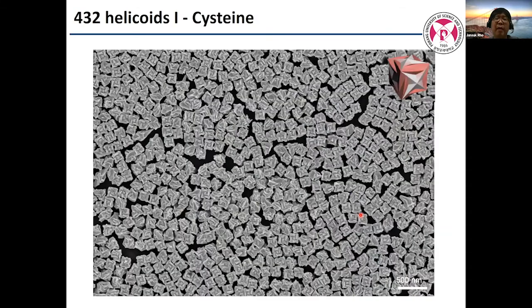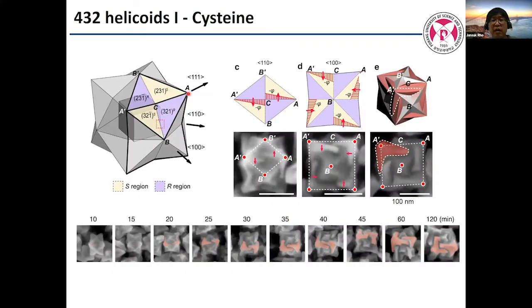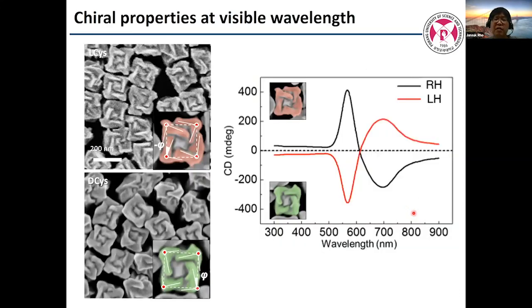So this is the macroscopic scanning electron microscopy image. You can see chiral shapes, not identical, but if we measure this ensemble, it's quite averaged out. So this is the case if we cut this plane, like 110, and this is the growing direction of this chiral tail, and 100 is like this one. And if you make a three-dimensional image, over a 2-hour process, the helical edge grows like this. And this is a self-stopping process after all the amino acid is gone.